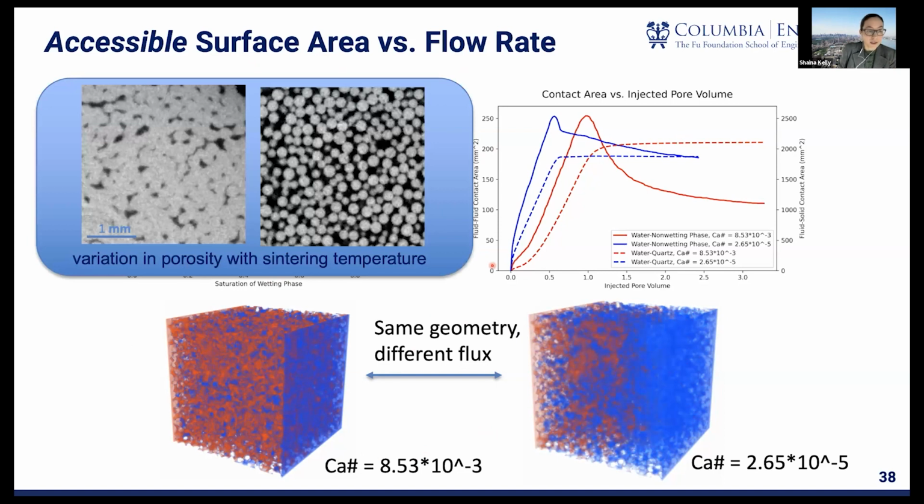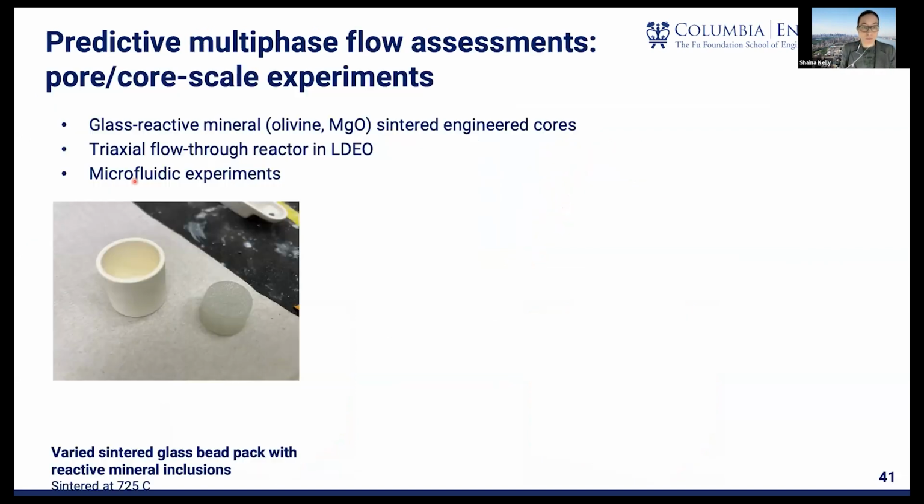Okay, and here are just some examples of the different bead packs the experimentalists on my team have been creating. This one is made by Rosie Krasnoff, and essentially you can create very idealized domains where we know what the porosity and perm is by controlling the sintering temperature.